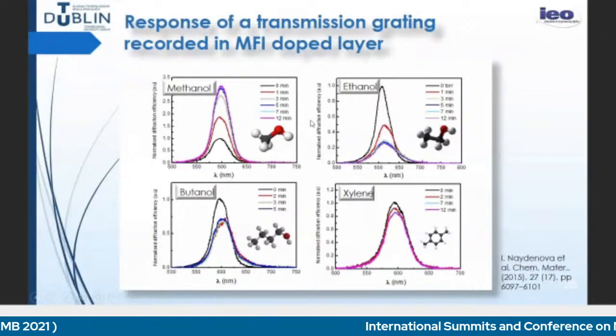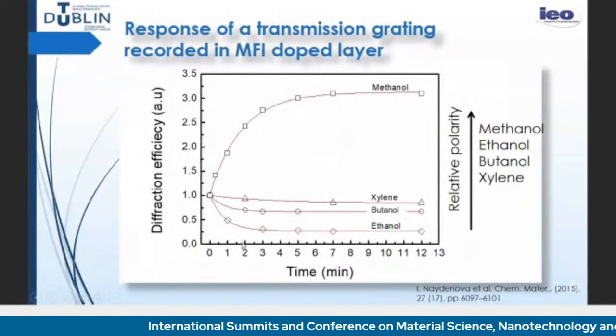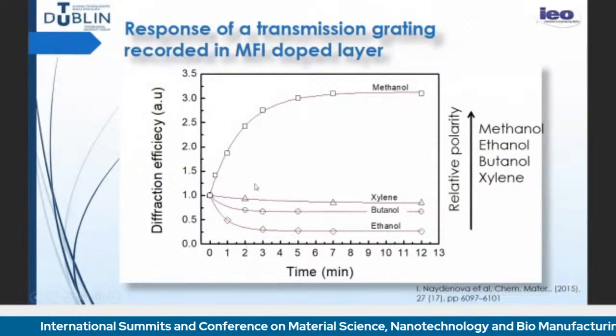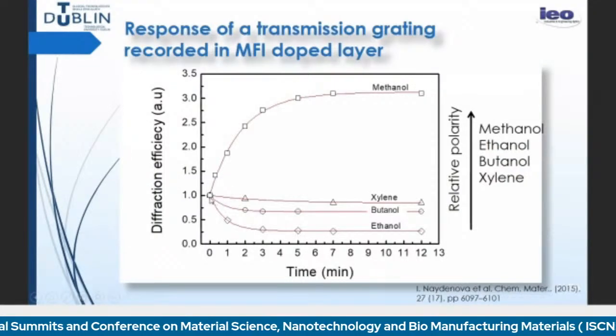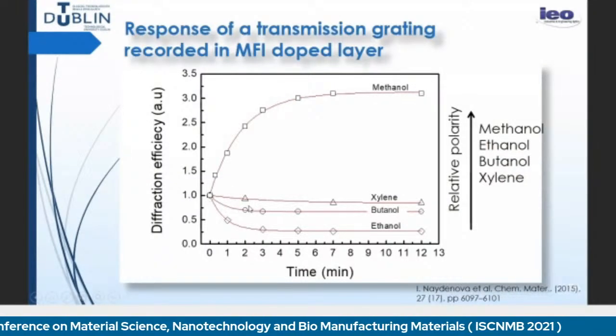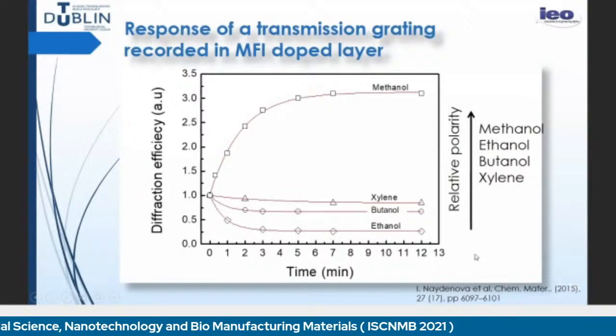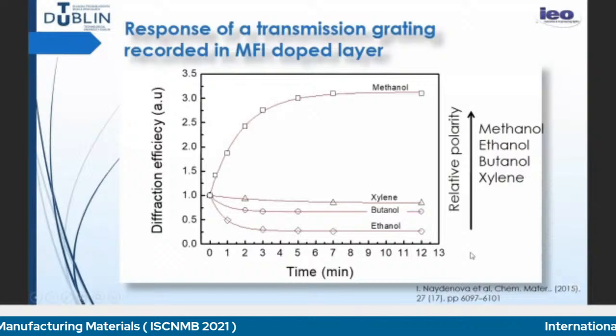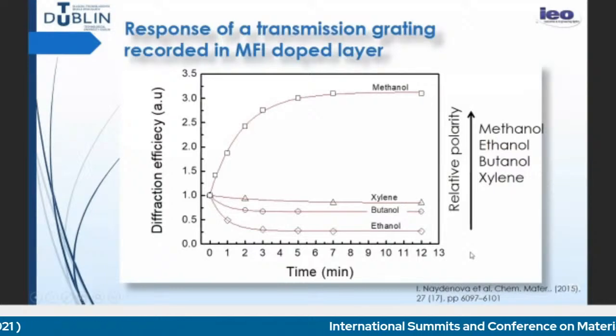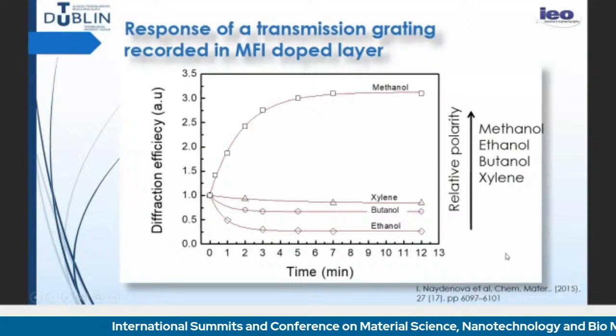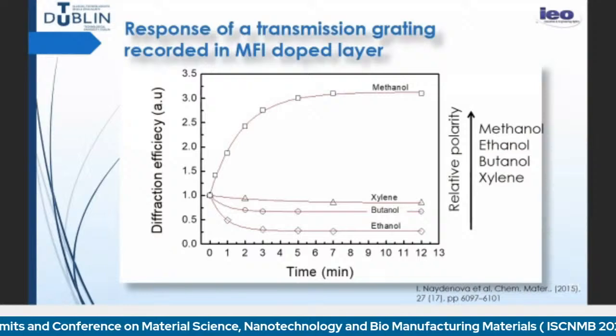We have taken the peaks and we have plotted them, and we see that the diffraction efficiency actually increases for methanol, for the smallest molecule with the largest polarity. And for the other molecules, it decreases. And we think that, first of all, it shows selectivity to methanol. And second, we think that this is due to the fact that the higher polarity maybe leads to swelling of the whole structure, not just the change of the refractive index modulation. We have further studied this.